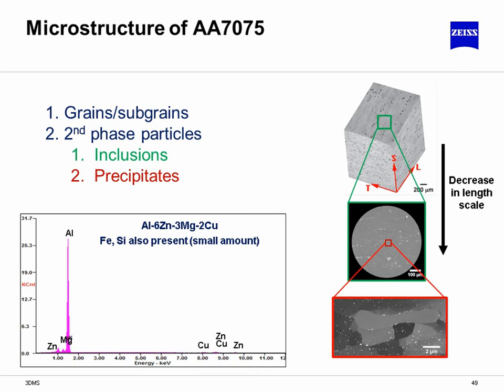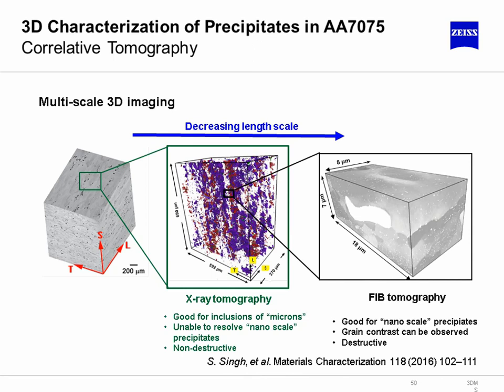Now, when they make these alloys, typically you'll have some impurities in here, but you'll also have some other elements in here that are intentionally placed in to strengthen the alloy. So principally, you'll have the aluminum grains themselves. You'll have second phase particles, such as inclusions, which are these larger, typically iron-bearing inclusions, so these bright white specks that you see here in this middle graph. They're maybe 10, 20, 30 microns in size. And then nanoscale magnesium-rich precipitates, which are intentionally placed into the alloy to strengthen the material.